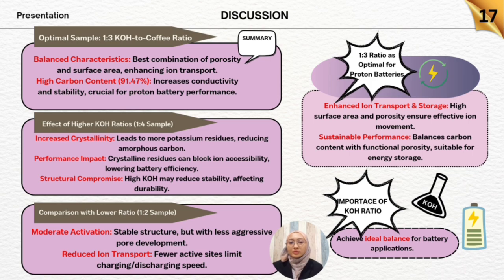So we move to discussion, where the optimal sample is the 1 to 3 ratio. The 1 to 3 KOH to coffee ratio sample emerged as optimal due to its high porosity, high carbon content, and stable structure. This balance makes it ideal for proton batteries, facilitating rapid ion movement for efficient charging and discharging.